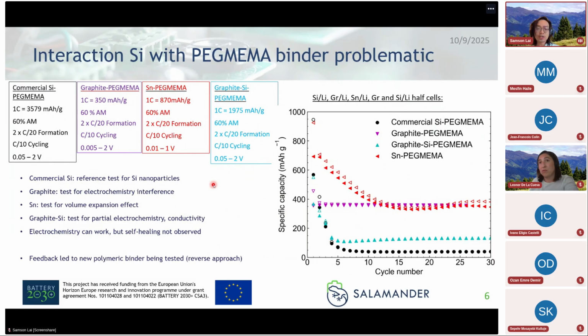So rather than having a self-healing polymer that we know has trouble with electrochemistry, we actually developed something that has good electrochemistry, shows that it can work, but now the self-healing is sort of the part that we need to tune a bit more. We had the same issue, actually, surprisingly, with the covalent adaptive network. So a totally different type of polymers, and still the same issues. So it was really a difficult time for our project to just start.